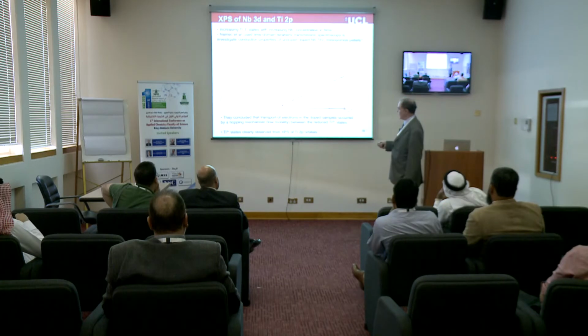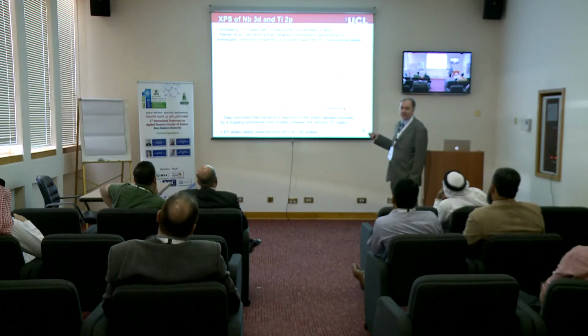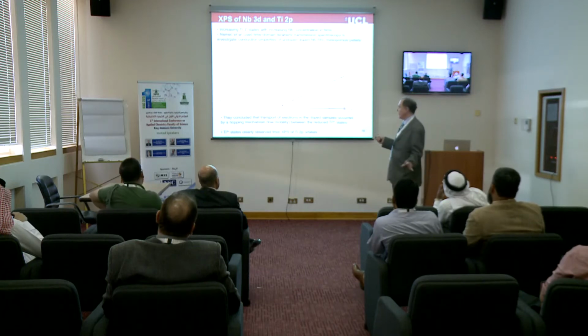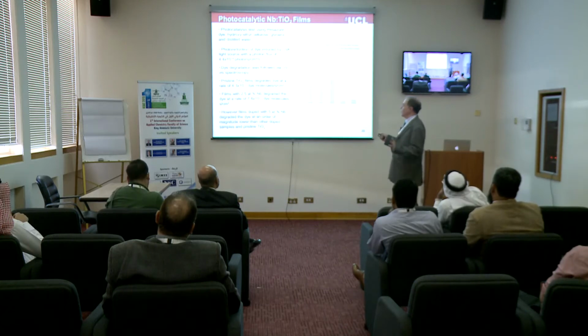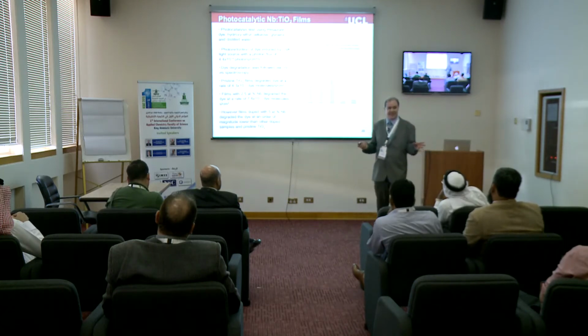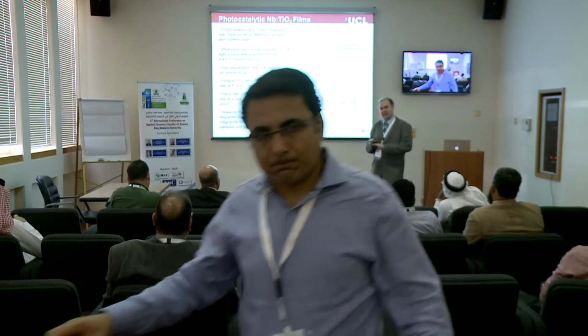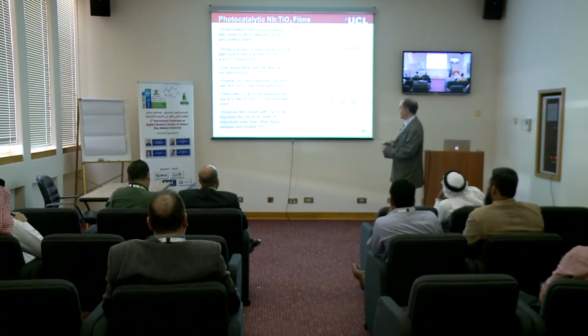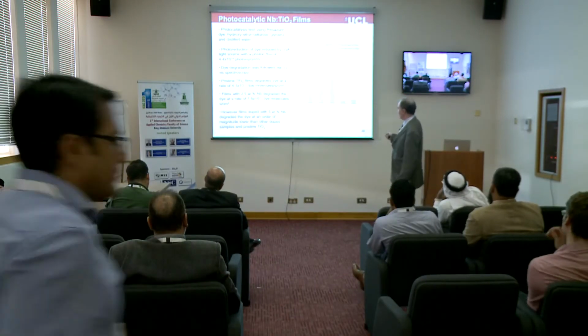So by doing XPS analysis, we find the blue colour comes from a small amount of titanium 3+ in our material, not from a reduced niobium 5+ to niobium 4+, which is what people have used via PVD. So this CVD method seems to give us some advantages. We also show that it works as a photocatalyst as well. So not only have we got the colour, we've got transparent conducting oxide properties, it also works as a photocatalyst.